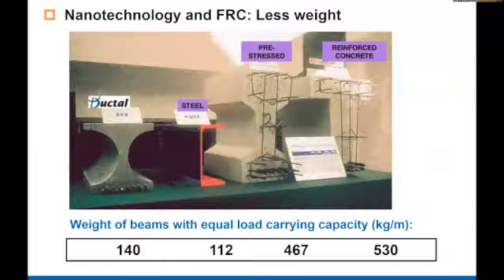For example, here I'm showing some slide that I took from Lafarge. And what they did, they tested 4 concrete beams. This one on the left is what they call Ductal, which is the ultra high performance concrete with fibers. Next to it is a steel cross section. Next to it is a pre-stressed one, and the last one to your right is reinforced. They all have the same moment carrying capacity, same so-called curvature ductility, but a big difference in weight per meter. So you can see that the so-called UHPC has the same weight as a steel cross section. So it's quite light, and this is one of the reasons why people have been using UHPC.